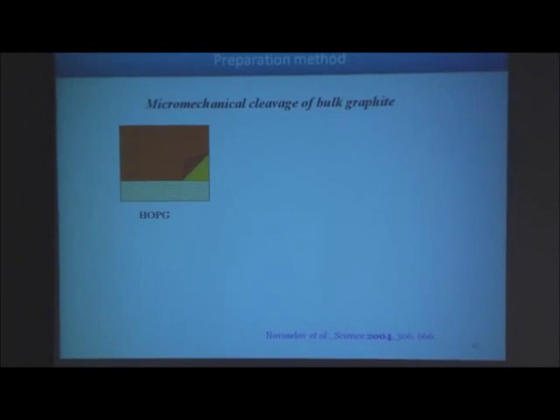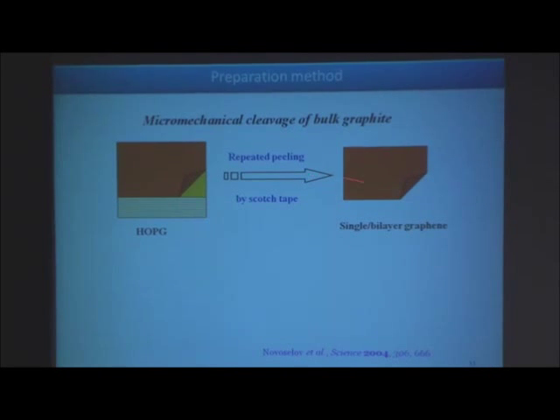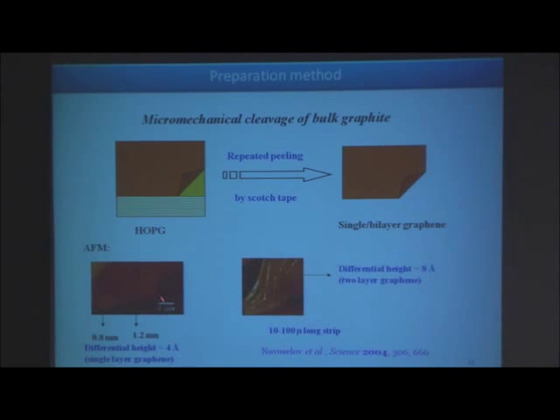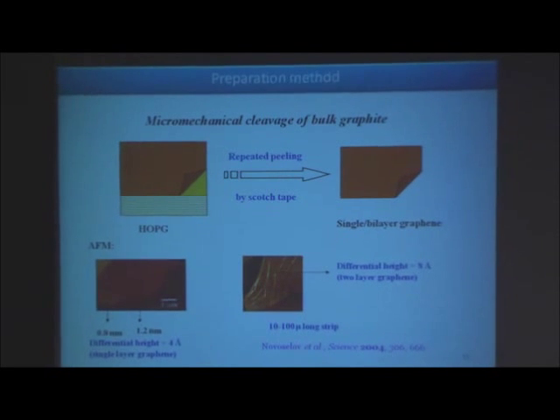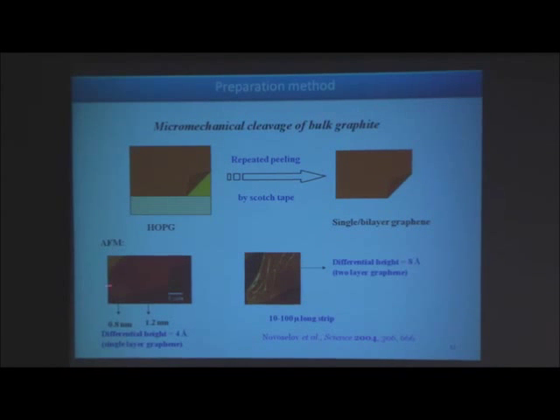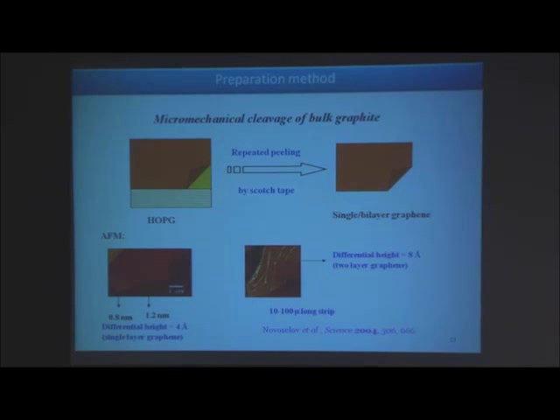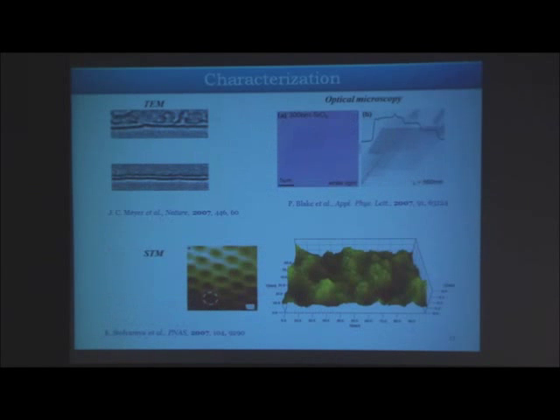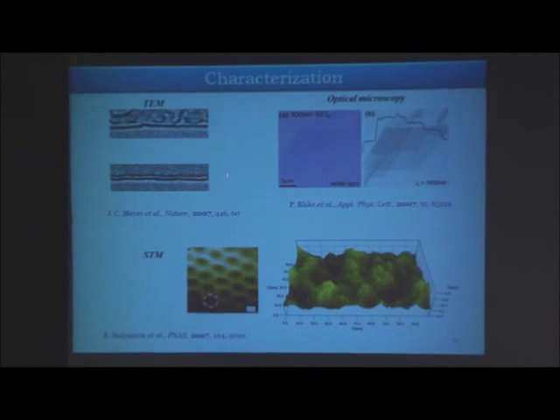They lift off one layer, and then you get a single layer, or you can even get a bilayer. And then you can take those things and do atomic force microscopy. You can measure the height of that layer. If it is 0.4 nanometer, it is one atomic layer. Therefore, it is single layer graphene. If it is 0.8 nanometers, it is two layers, it is a bilayer graphene. Well, once it was done, you can do all the characterization. This is from the early work that came in the Proceedings of the National Academy of Sciences in 2007, just 3 years ago. You can see the single layer, two layers, you can get two lines.